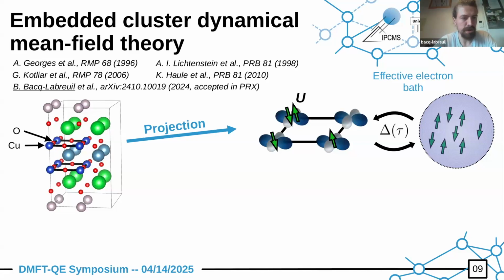So imagine that you have your crystal structure on the left with the copper and oxygen planes. So here I took the example of a cuprate, of course. Then the idea is to say, well, we have this full crystal structure with all its degrees of freedom in which we cannot treat the electronic correlations because it's too complicated. So what we do is we project. So imagine that, in the same spirit as DMFT on the Hubbard model, you would project all the degrees of freedom which are around this cluster of copper, all right? And you would get basically into an effective impurity problem where you have, in our case, 4 copper, so a 2x2 plaquette impurity. And on each copper here, we will only keep the dx squared minus y squared orbital, which is the one that lies basically at the Fermi level and which forms this Zhang-Rice singlet.